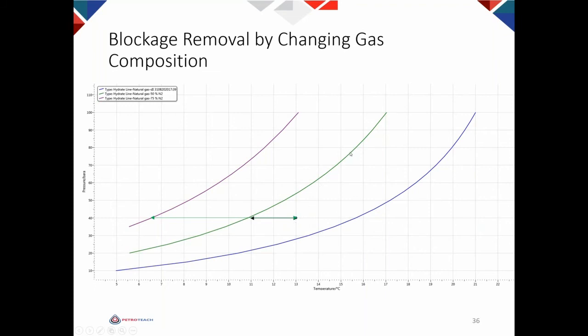Now, for example, this is 50% nitrogen. You see the phase boundary shifts to the left. Therefore, hydrate can dissociate. If I put enough nitrogen to make the gas composition 75%, then you can see the driving force is higher. So changing the gas composition also can be used for melting hydrate blockage.